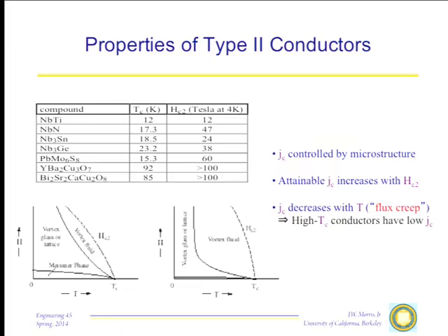But the other application for them, this very high critical field, means that if you want to make a magnet that has a huge field, you need a superconductor down at the core where that field operates that has a very high critical field. So you find these oxide superconductors being used in the cores of very high field magnets, 30, 40 Tesla magnets, to take advantage of this high critical field down at 4 degrees Kelvin. And of course down there you don't have to worry about thermal activation, so you can get decent currents through those superconductors. But that's basically what happens.